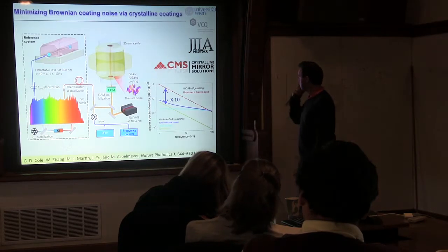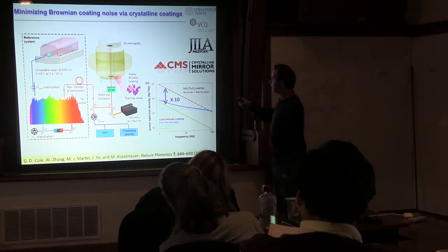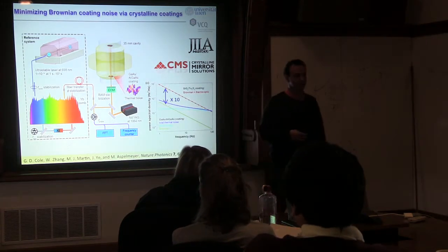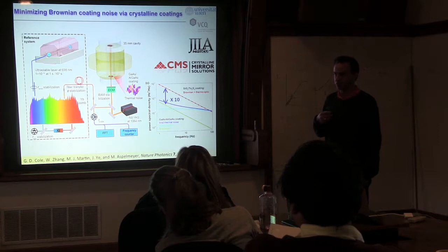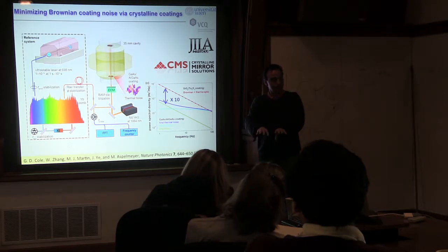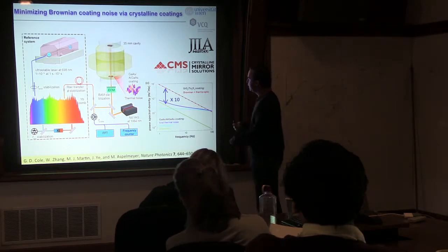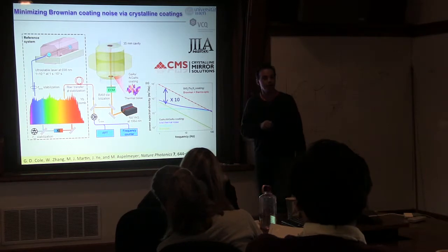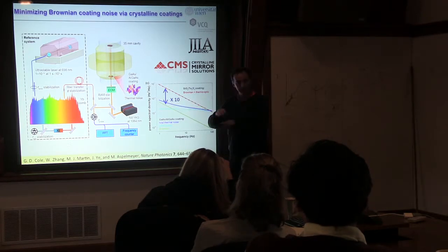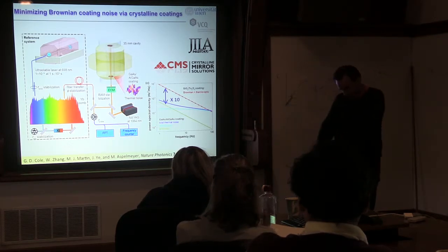And then together with the group of Jun Ye and Schiller, we compared the performance of this cavity with their best optical cavity that they had. So this is the local oscillator for the strontium clock that is there. Basically we compared the noise performance of these two cavities, and from that data we inferred the amount of coating thermal noise in the system. And lo and behold, we reconstructed and demonstrated that we really get a tenfold decrease according to the mechanical quality factor improvement of our coating. So this was really directly on the prediction for the ideal case.